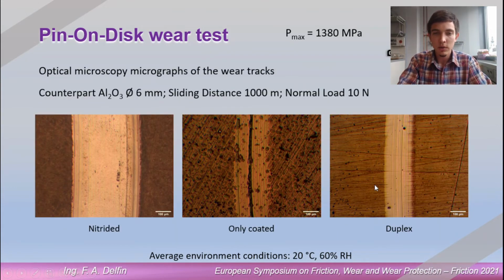And here you can see the optical microscopy of these wear tracks. Of course, nitrided is really wide. It has some grooves on it, but the coated samples are slightly thinner. They seem a little bit better, but the only coated sample has this stripe here in the middle, which we